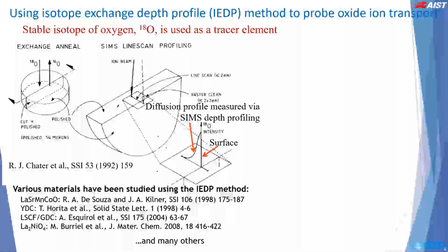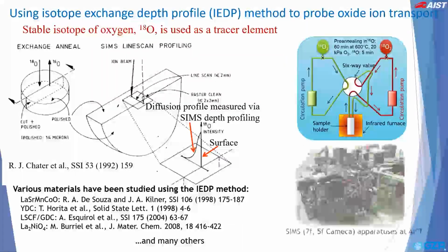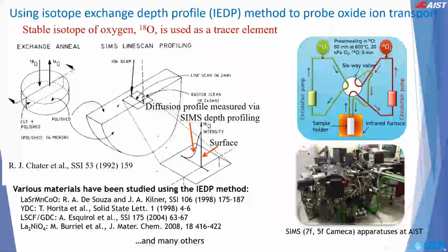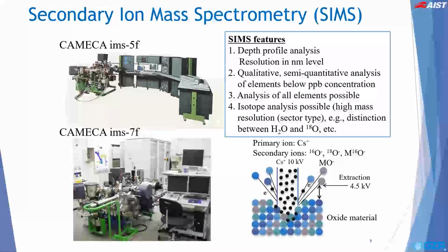This is the schematic illustration of the isotope exchange setup, and here is a photo of the SIMS machines used at AIST, namely 7F and 5F models. There are specific SIMS features which make it an attractive analytical method for SOFC research. First of all, depth profile analysis is possible with very high resolution at the nanometer level. For devices like SOFCs, which are comprised of heterostructures of various thicknesses, being able to probe the layers from the surface down to the buried heterointerfaces allows us to extract important information, for example, about cation diffusion phenomena occurring across interfaces.